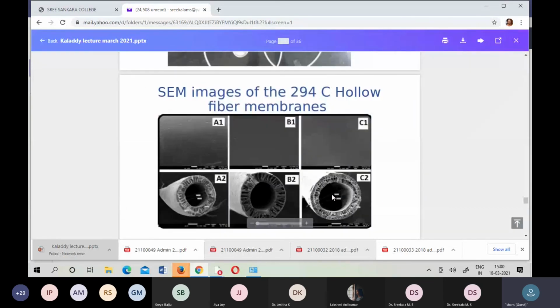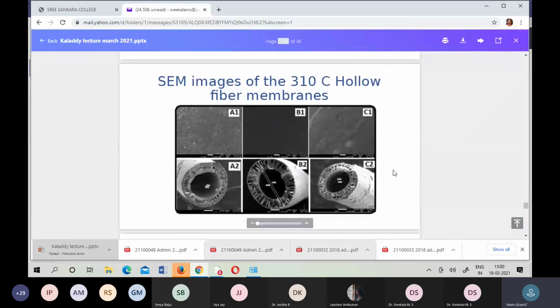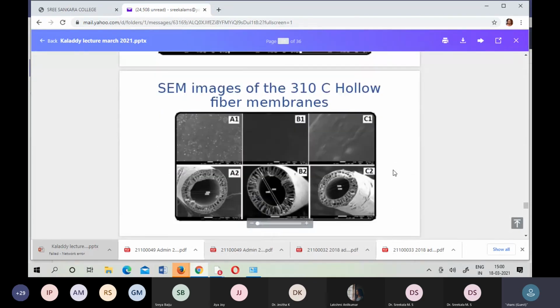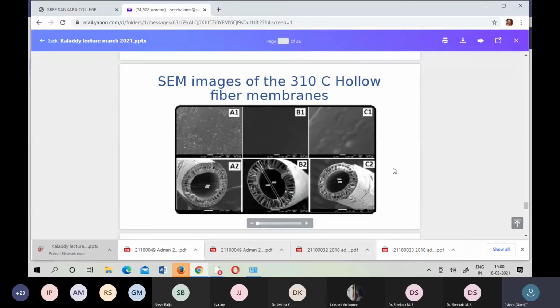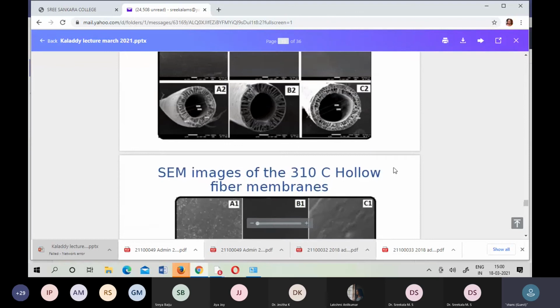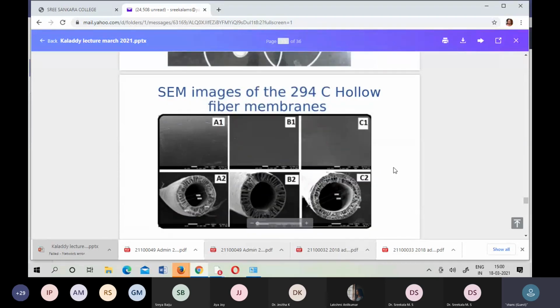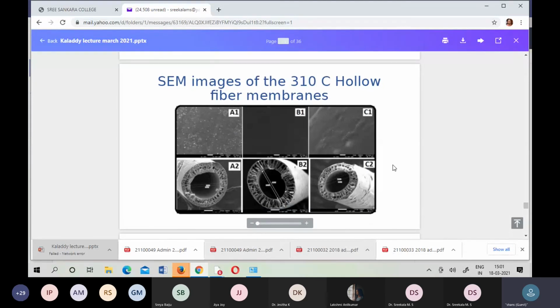Once we prepare the coating and the membranes are coated, we put them in the oven at 40 to 60 degrees to dry them, making sure the membranes are not breaking, because we can't keep them at high temperature. Once the hollow fibers are coated with chitosan, we prepare the module. For each module, I think I kept 10 hollow fibers, and we have a specific epoxy resin. We need to apply resin here and here. It's a 2-3 day long process to make a module, and we keep it in a vertical position so that all the hollow fibers are aligned, with no bending or damage.